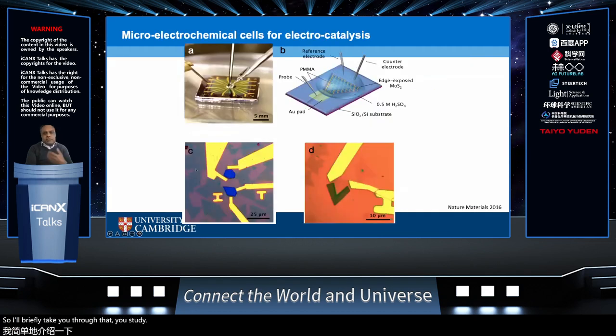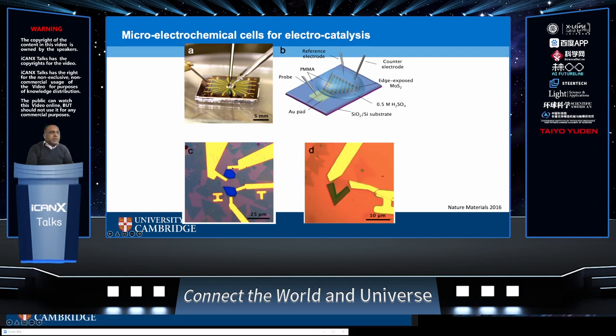To study the influence of charge transfer resistance and also the influence of different phases on the catalytic activity, we pioneered these microelectrochemical cells. These are little tiny HER reactors that we fabricate using lithography on a single flake of molybdenum disulfide. So we typically grow molybdenum disulfide by chemical vapor deposition. You might be able to see the triangles behind.